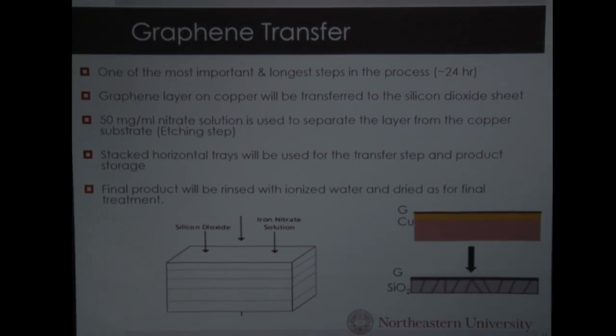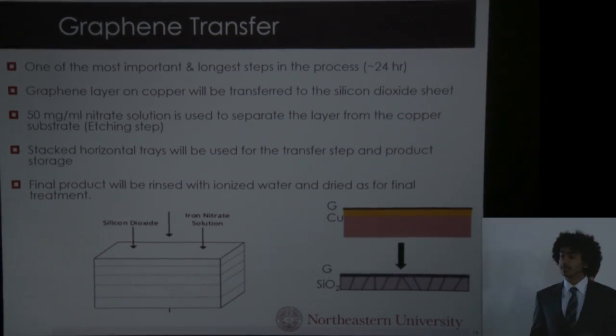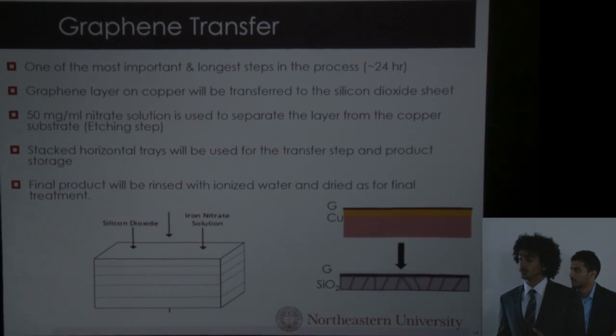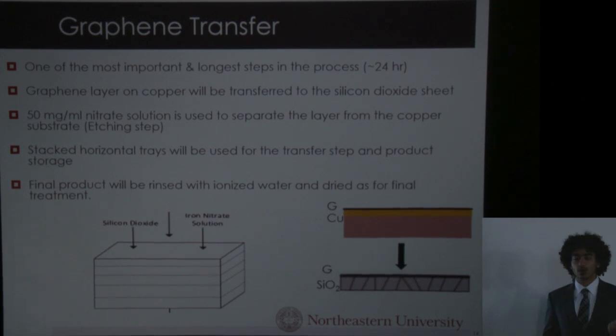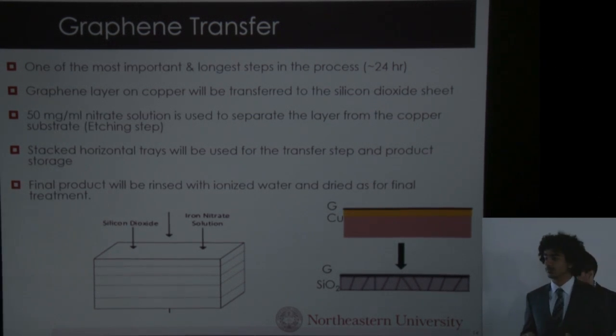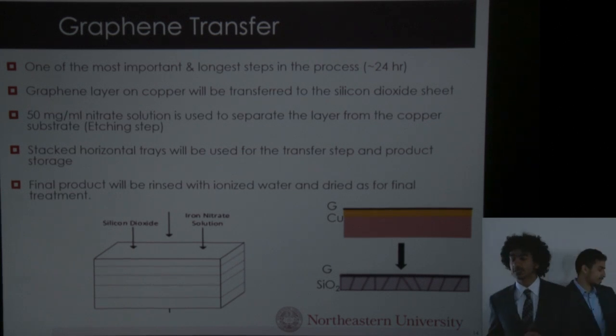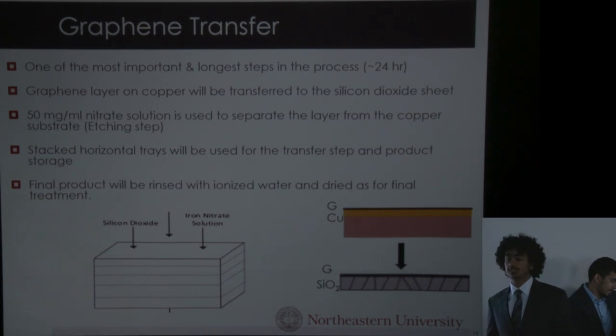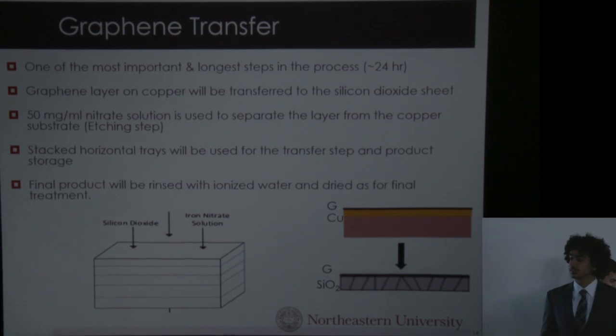After graphene on copper layer leaves the reaction furnace, it needs to be transferred to an SiO2 layer to be used in touch screens. It is the longest part of our process. The idea is pretty simple. We place the graphene on copper layer in a 50 milligram per milliliter iron nitrate solution and wait for the copper to be etched away. After we carefully remove the copper layer, we place an SiO2 layer for the graphene to be deposited on it. We were able to speed up that process by having stacked trays of iron nitrate solution, and that enabled us to save space and time and get to our production rate of 76 million centimeters squared yearly.